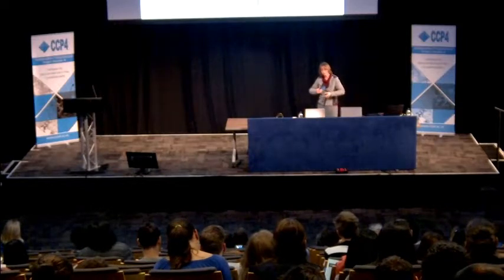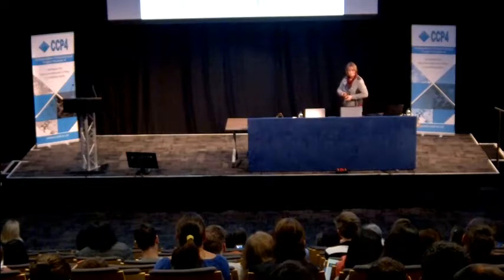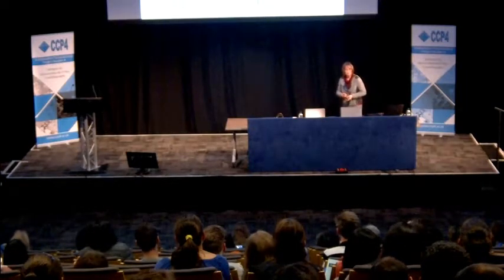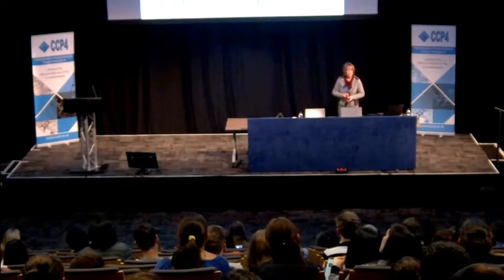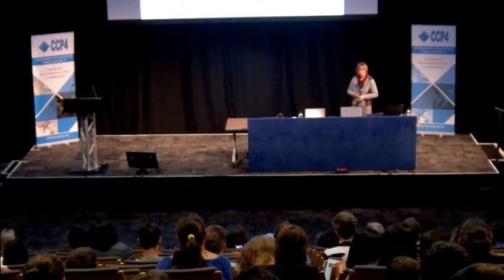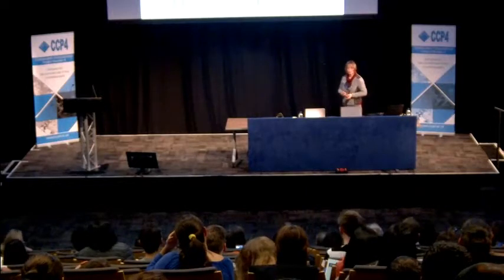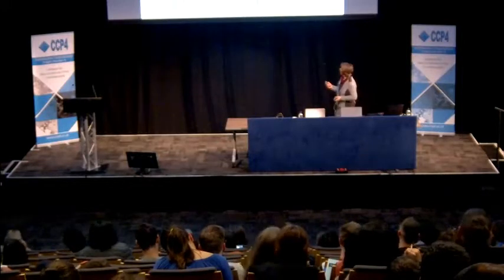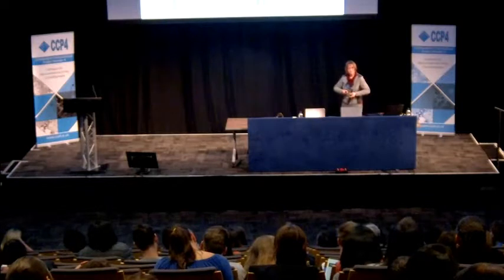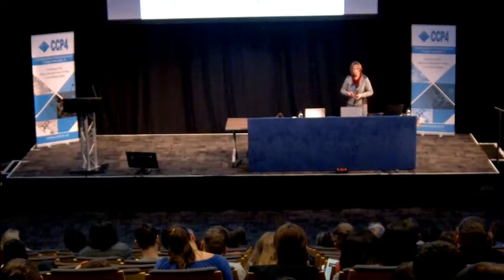Of course, normally you don't have this red and blue coloring, so you must identify which reflection belongs to which domain. If you think of a reflection list used to index this reflection pattern, assuming we have two reflections in the list that would lead to a cell axis which is much too long — so the first problem is cell determination, and that could be problematic. You can identify this kind of twinning because of these three types of reflections. Because you will have a lot of reflections contributing to only one domain, you can easily detwin the data, meaning that even if it's a 50-50 twin, you can detwin the data. Then the reflection file has no longer the information of twinning, and structure solution is not as problematic as for merohedral twins, and neither is the refinement.